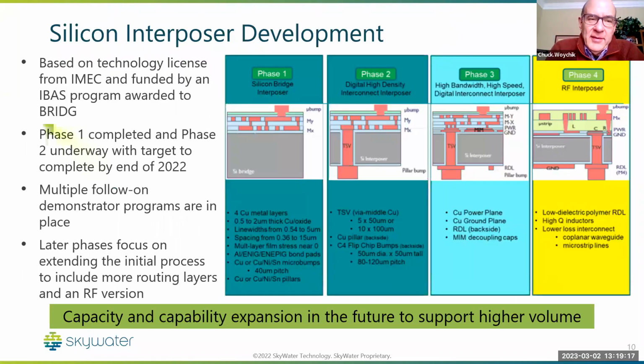So what I'm going to talk about now is our core platforms at SkyWater. The first one being the silicon interposer. As was previously mentioned, what we are doing is work with BRIDG, and this is based upon a license from IMEC technology. So the IMEC license technology is being used in this IBAS program to create these 4 different phases of silicon interposer. The first phase being a simple bridge interposer, and this activity is a 4-layer buildup structure, copper damascene, on a fully thick silicon interposer.